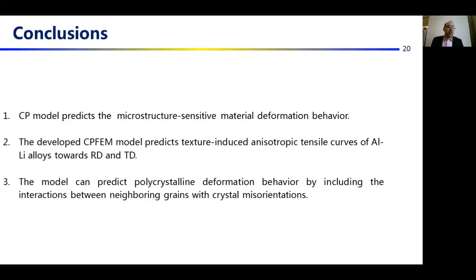As for the overall conclusion, the CP model can predict the microstructure-sensitive material deformation behavior. The developed CPFEM model can predict the texture-induced anisotropic tensile curves of aluminum-lithium alloys in the rolling and transverse directions, and the model can also predict the polycrystalline deformation behavior by including the interaction between neighboring grains with crystal misorientation.